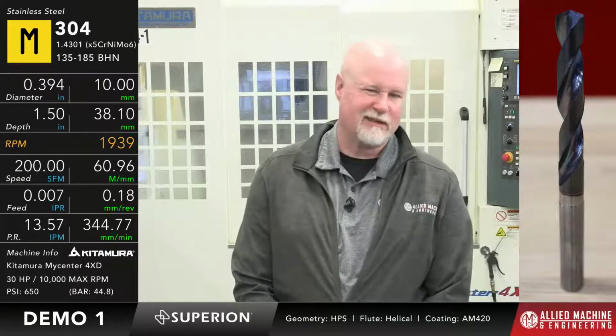Speed and feed we're going to run is 200 surface feet a minute, which is just about 61 meters a minute in velocity, and a feed rate of 7 thou per rev, or 0.18 millimeters per rev. That's going to result in right around 13.5 inches a minute, or 344 millimeters per minute penetration rate. Once again, the material is going to be 304 stainless steel, hardness about 160-ish Brinell. So it's relatively soft stainless steel.